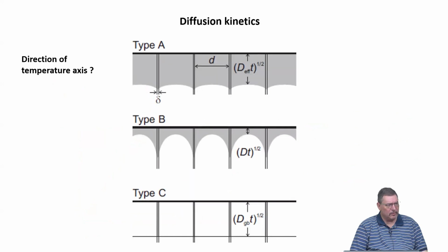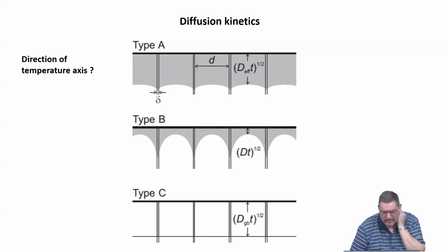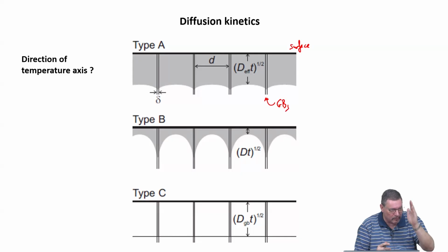So we are now going to grain boundary diffusion, right? We have cut out the surface, no dislocations. This is then a simplified view. We have an open surface, which has been nicely polished to mirror finish. And we have some grain boundaries in the material. And for the sake of simplicity, they are all arranged in a way that they would perpendicularly cut the surface. They have an average distance d and a thickness delta.